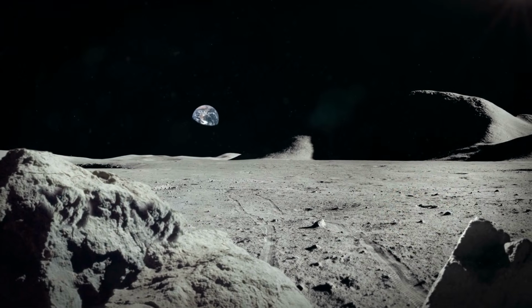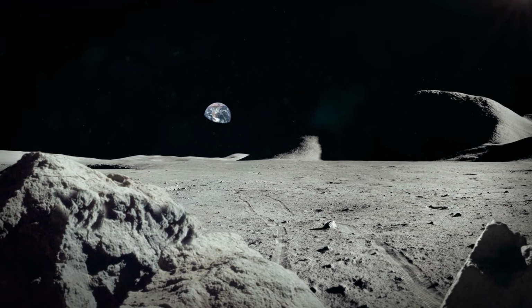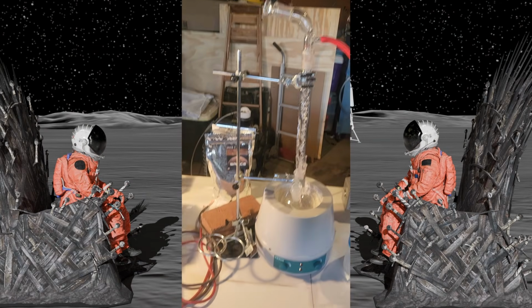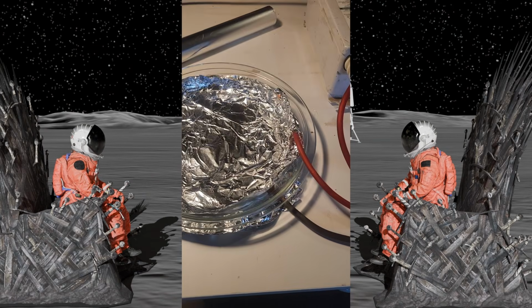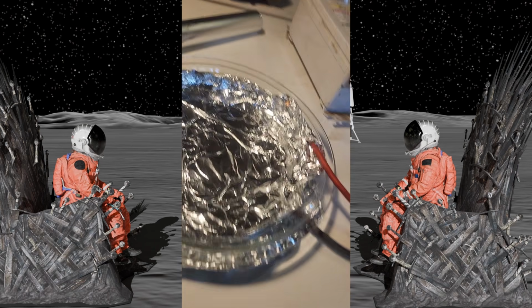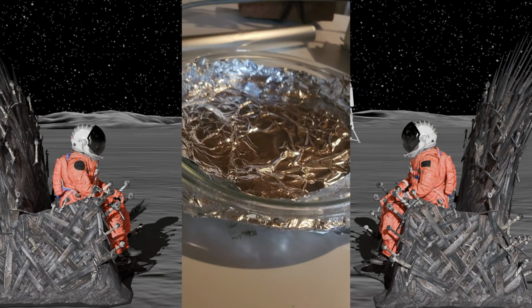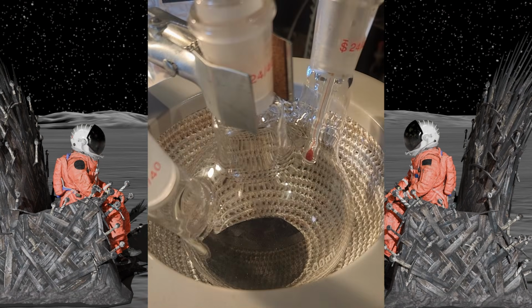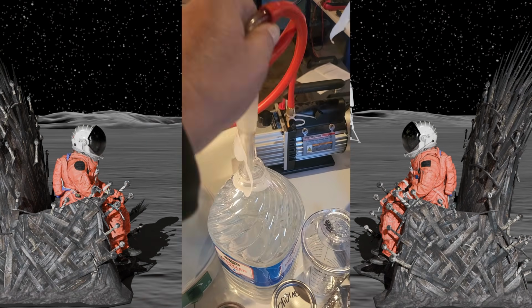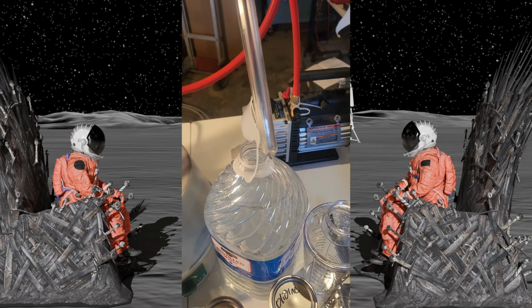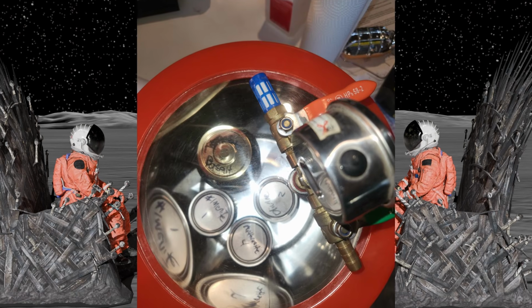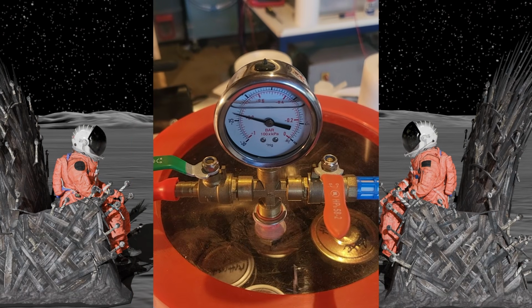So yes, exactly. One of the things that we need to do is simulate as best as possible the lunar environment. When you receive the simulant, whether it's from a supplier or you're making it yourself, one of the things you need to do is basically give it a round of what I call the lunar treatment. First, we took the simulant and subjected it to 9 kilovolts, approximately 300 milliamps, for approximately 30 minutes or so to make sure that the particles all have an even charge. After that, we took it to vacuum dehydration, where we heated it up to about 200 degrees Celsius and performed vacuum dehydration on it. From there, we purged the system with argon. Then we canned them up and stored them in a mild vacuum chamber under argon for our next process.